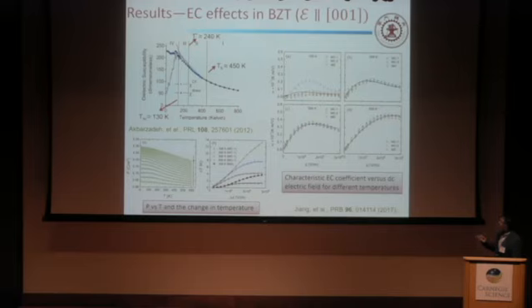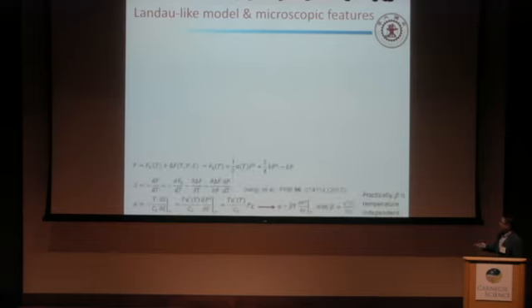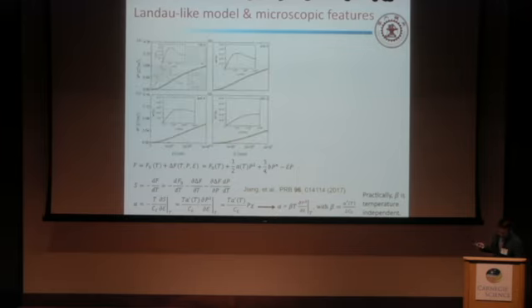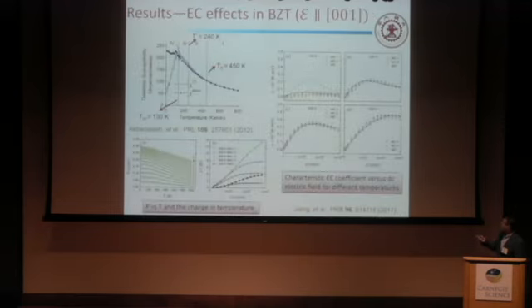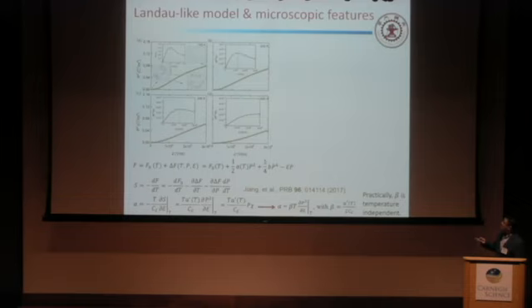To understand the EC response as a function of electric field, based on the Landau model, alpha is proportional to the derivative of P squared with respect to the electric field. In other words, alpha is proportional to this formula. To verify this model, we calculate the square of the polarization as a function of electric field, then take the derivative. We can find that the trend is the same as what we found before. This is the EC coefficient as a function of the electric field. The Landau-based model can also reproduce this trend.